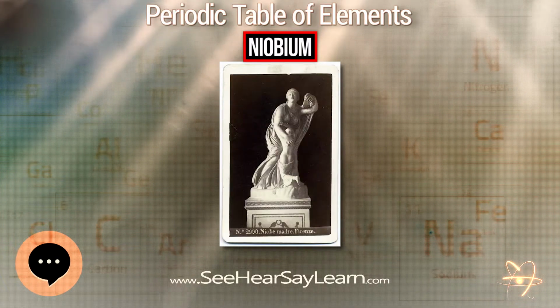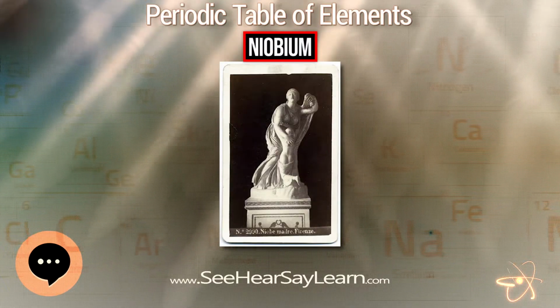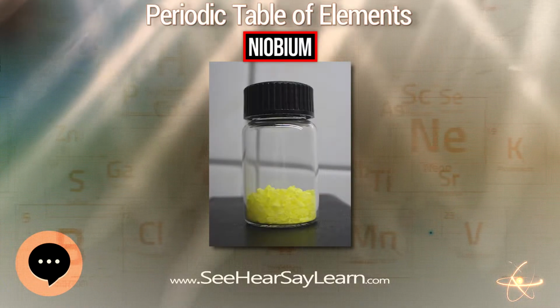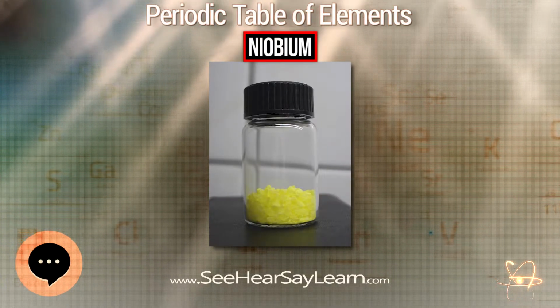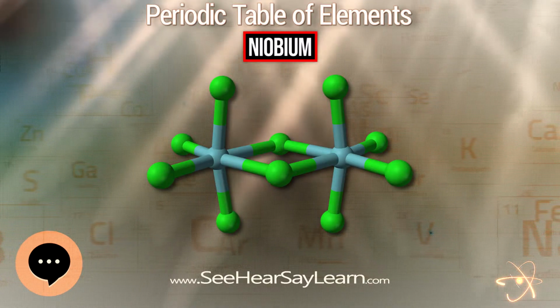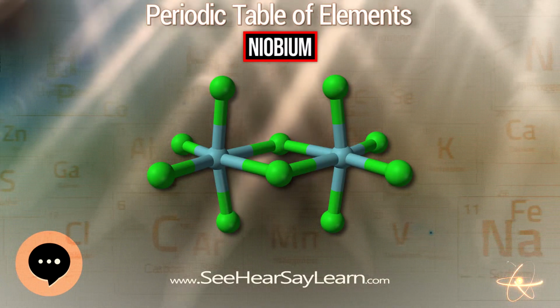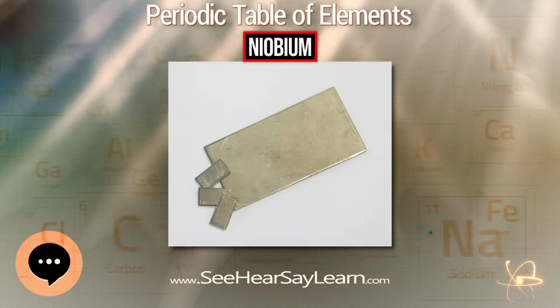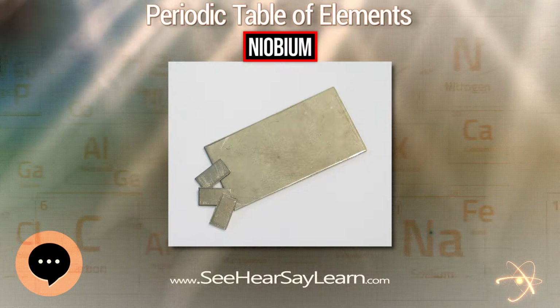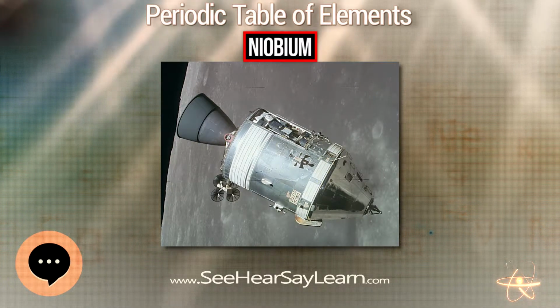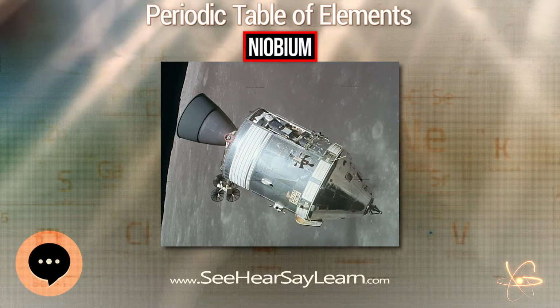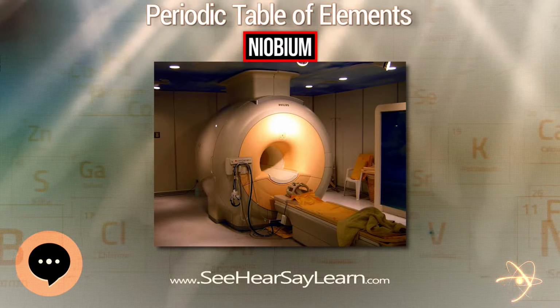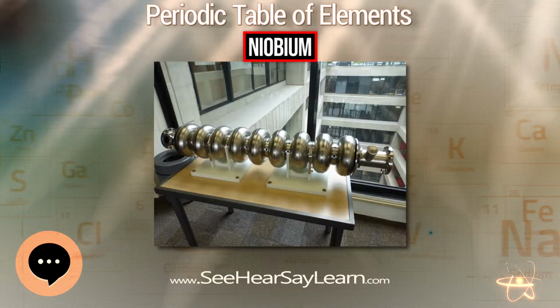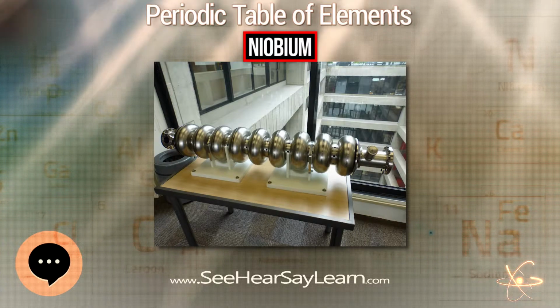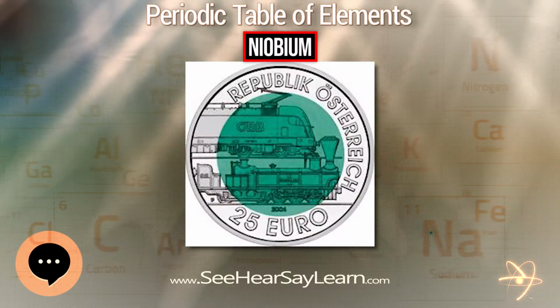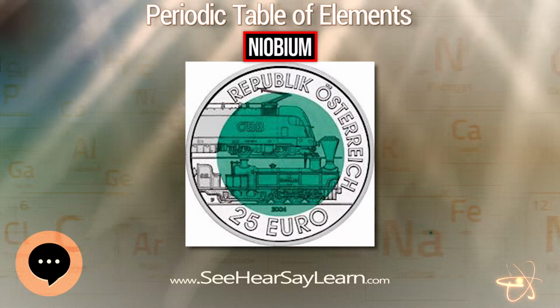The complex niobium and tantalum fluorides are extracted separately from the organic solvent with water and either precipitated by the addition of potassium fluoride to produce a potassium fluoride complex, or precipitated with ammonia as the pentoxide. Followed by this, several methods are used for the reduction to metallic niobium. The electrolysis of a molten mixture of K2[NbOF5] and sodium chloride is one; the other is the reduction of the fluoride with sodium. With this method, a relatively high purity niobium can be obtained. In large-scale production, Nb2O5 is reduced with hydrogen or carbon.